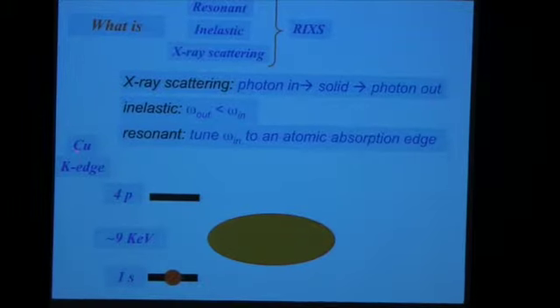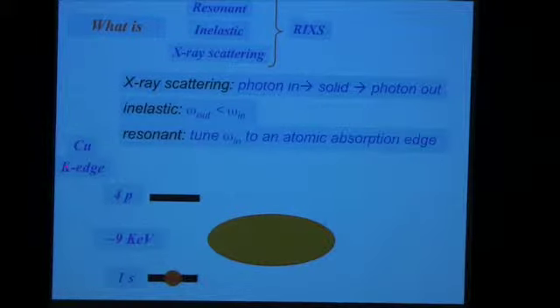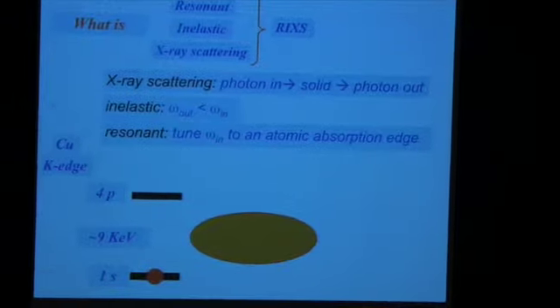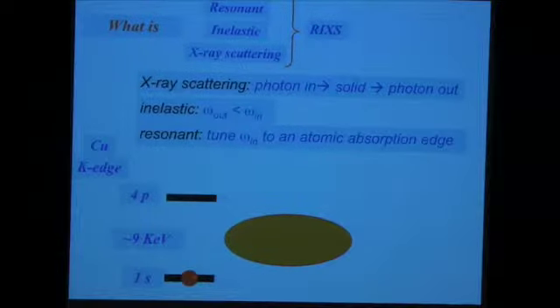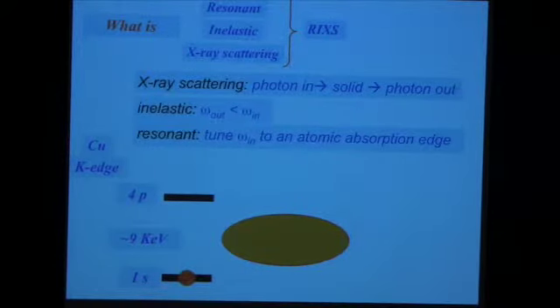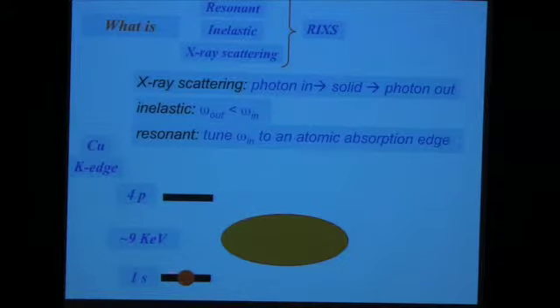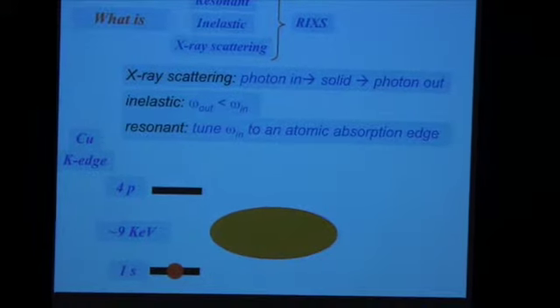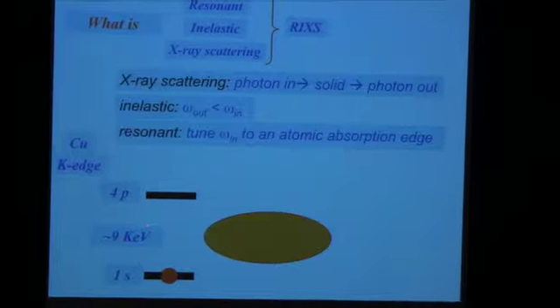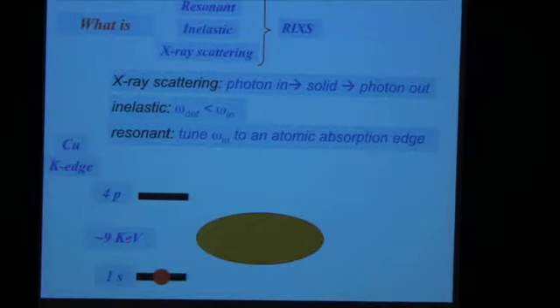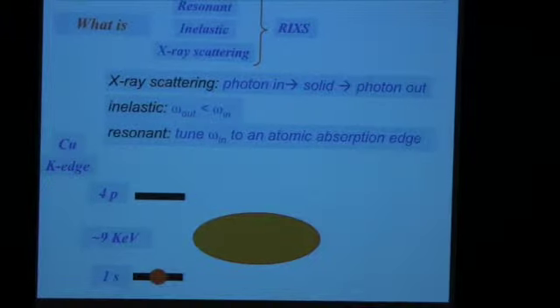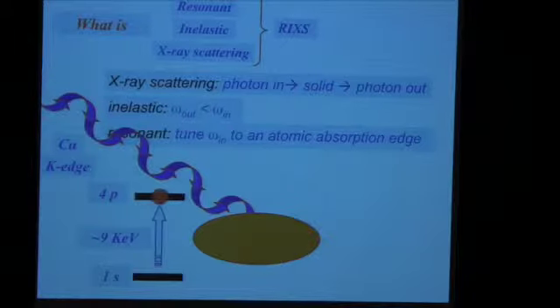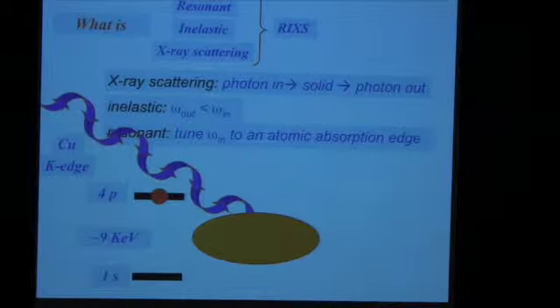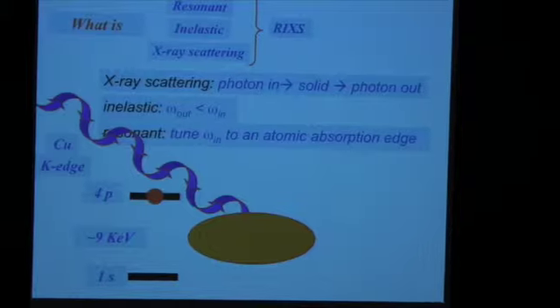For instance, if you do RIXS at a copper K-edge. What does K-edge mean? It implies you start with an electron deep in the core, a 1s electron, you add 9 keV of energy to it with a photon, and you promote it to a 4p excited state via a dipole interaction.